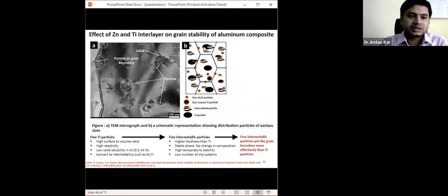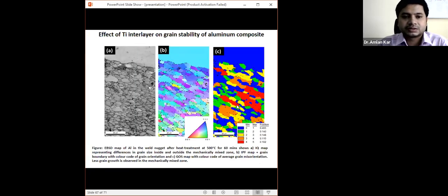This I have represented schematically here. We can see some of the particles are sitting at the grain boundary, as well as particles sitting in the matrix material. The fine particle, which is mostly intermetallic particle, has high temperature stability, and does not degrade as well as react at high temperature. So this particle sits at the grain boundary and pins the grain boundary mobility. The same thing has been also observed when the titanium particles are distributed in the matrix material. You can see here, this is outside the process zone, and this is the process zone. From there you can see that grain stability is substantially higher in the composite material.